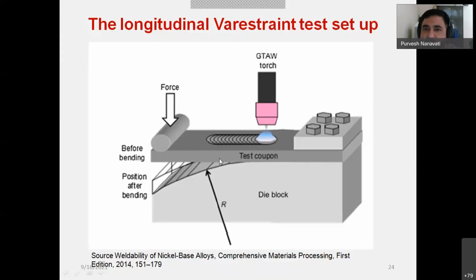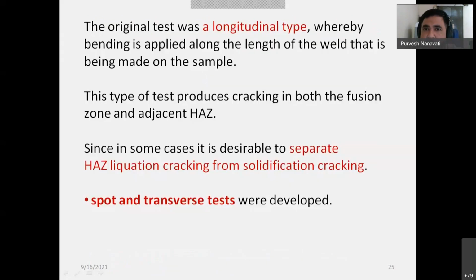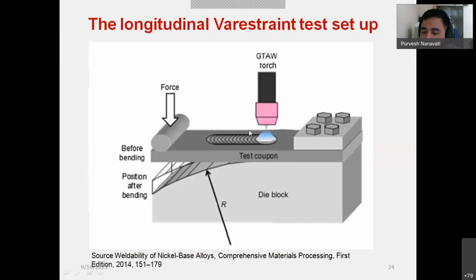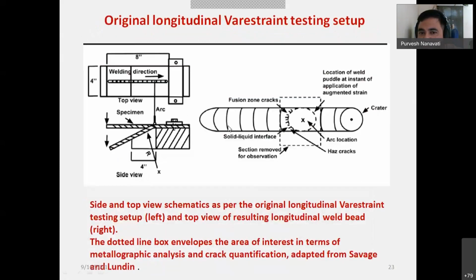Okay. Now this is a test setup for the longitudinal Varestraint test. Because the weld is along the longitudinal direction, it is simply known as the longitudinal Varestraint test setup. This is the original test, the same information which I have given you. This type of test produces cracking in both the fusion zone and the adjacent heat affected zone, as you could see from the previous picture, because of the bending stresses produced by the force applied from the top. This area will be bent, and so the fusion zone and the heat affected zone will be under stress.